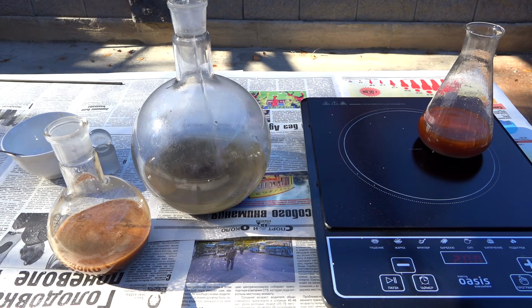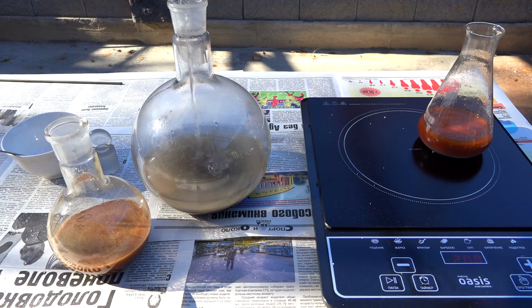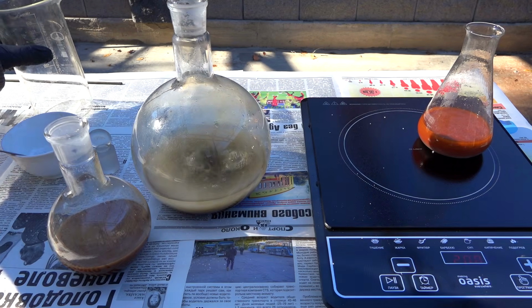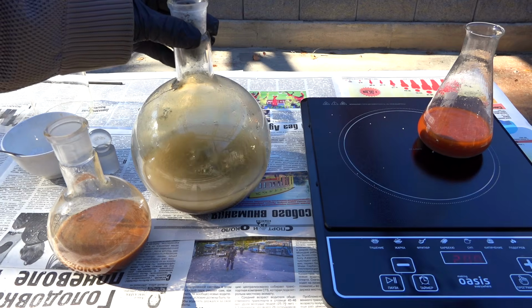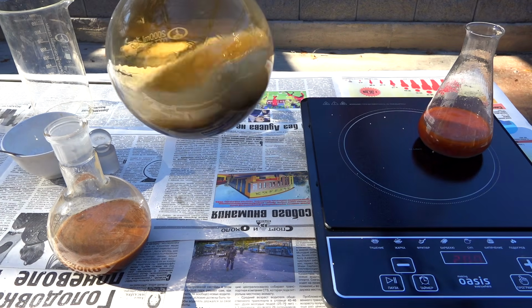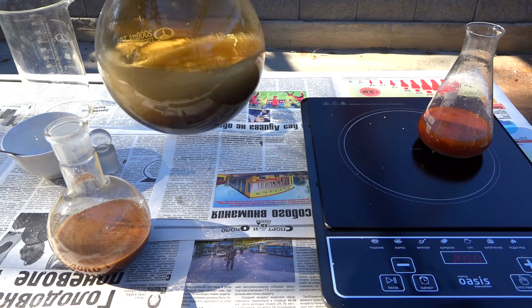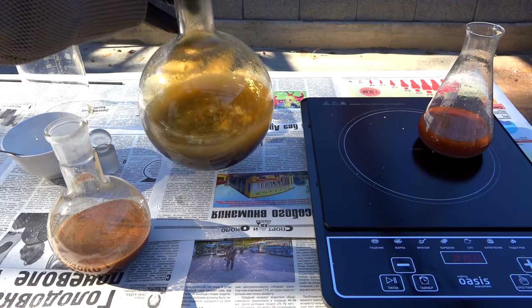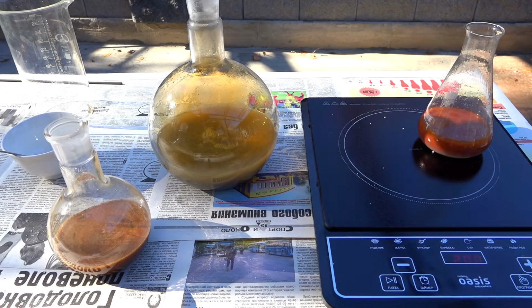As soon as I add nitric acid, a reaction begins immediately, as can be seen by the characteristic brown vapors. Nitric acid oxidizes sodium chloride, releasing chlorine gas, which dissolves the gold. A large amount of chlorine is released, so all work must be done under a fume hood or in an open area.